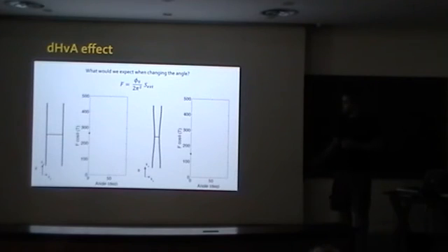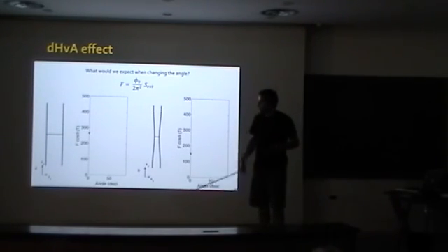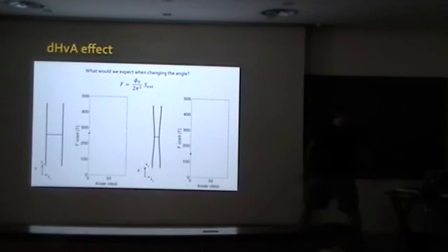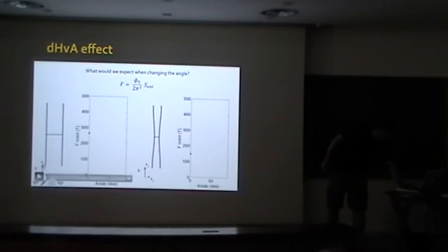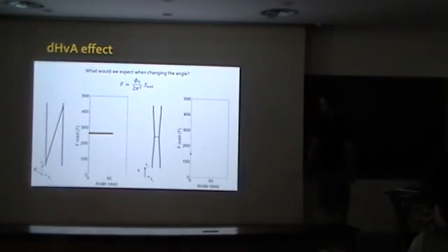But what we would also like to know is how the Fermi surface looks in three dimensions. What I draw out here is a perfectly two-dimensional cylindrical Fermi surface. If we do those measurements and change the angle of the field, we basically probe a different extremal orbit. And if we plot the frequency that we observe times cosine of theta, we just get a straight line. So this would be perfectly two-dimensional.